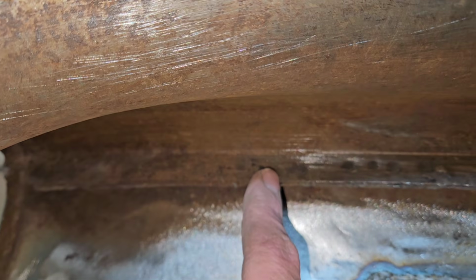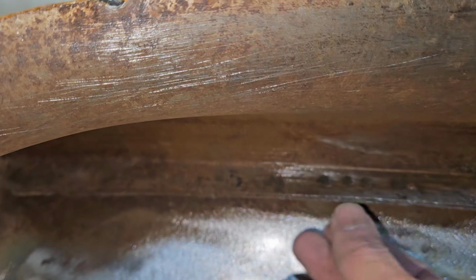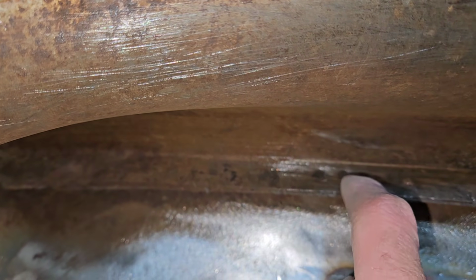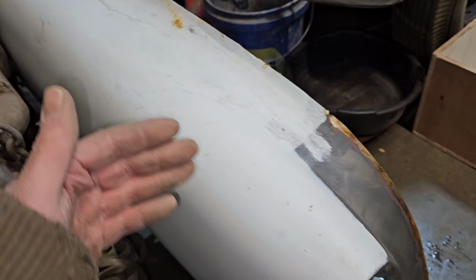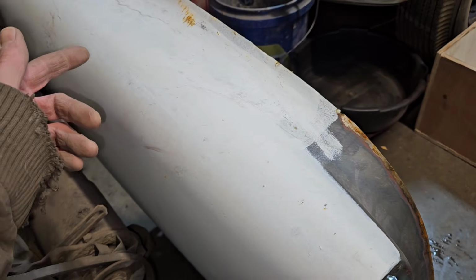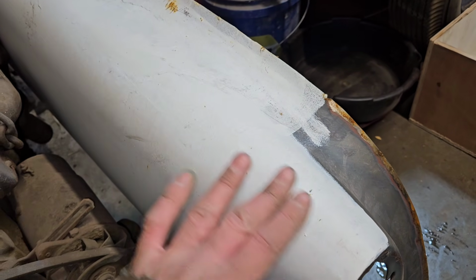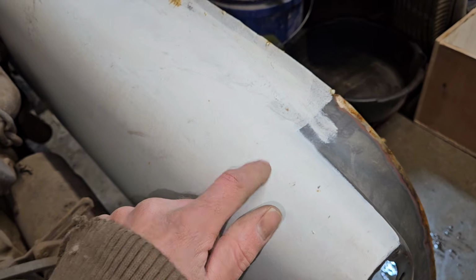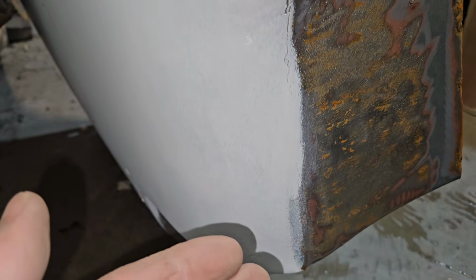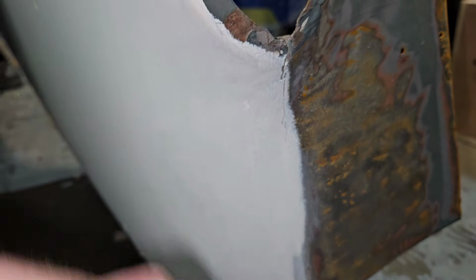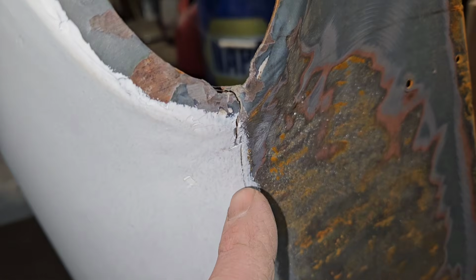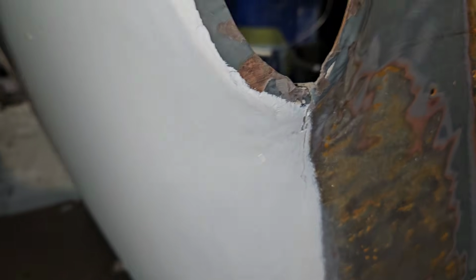Here's that same style of seam on a 1953 Chevy quarter panel. You can see, however, instead of butt welding it, they have a flange, and it's been lap welded. On the outside, that seam was filled with lead and filed smooth, and it's actually holding up well at the top here. However, down at the bottom, where moisture can get into that lap weld, we can see that it's started to crack and fail.